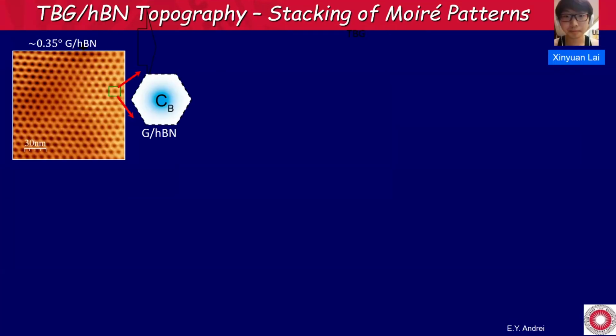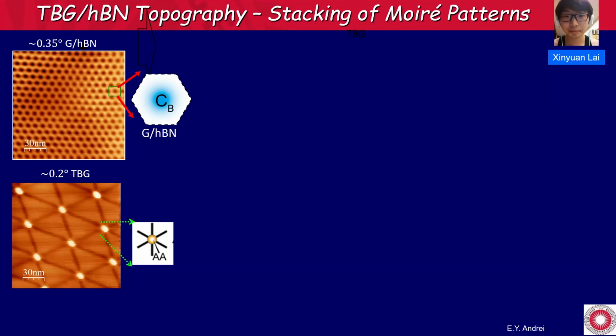So, first of all, what are we looking at? If you just put graphene on boron nitride, you see these dark spots here. These dark spots correspond to the lowest energy state where carbon is exactly aligned to boron, and there's a bright halo around it. When you do twisted bilayer graphene by itself, the brightest regions here are the AA regions.